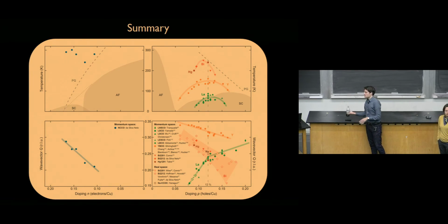Typically, you track that as a function of some experimental parameters like doping, or temperature, or pressure, or strain, or magnetic field, to look at how that particular electronic order is affected by these experimental parameters. So is it suppressed? Is it weakened? Is it enhanced? The amplitude basically gives you a measure of the global order parameter that's associated to that particular electronic order.